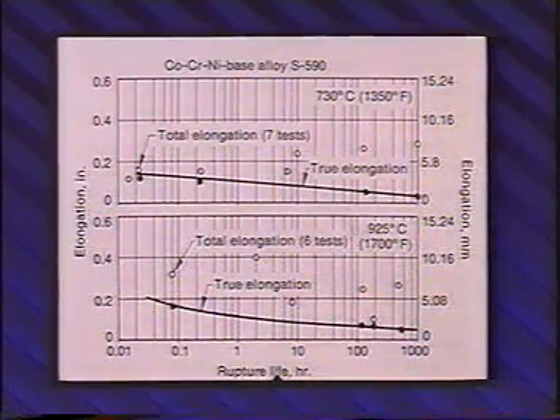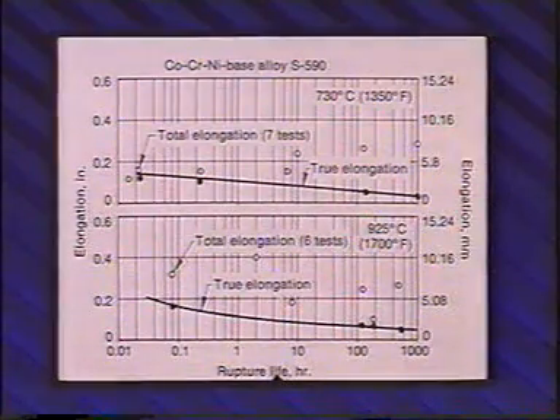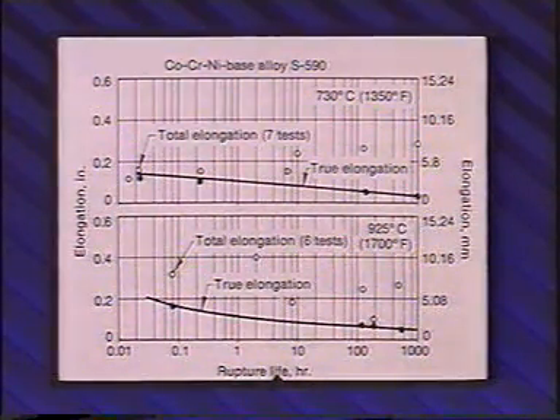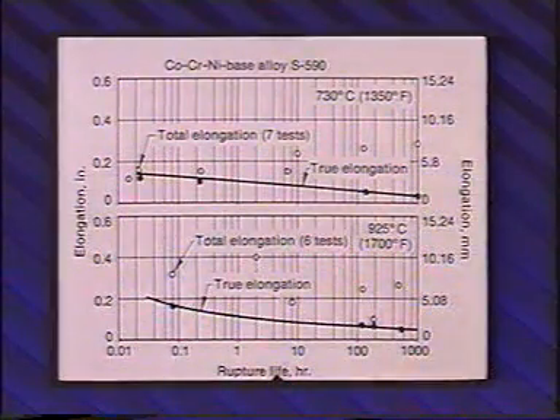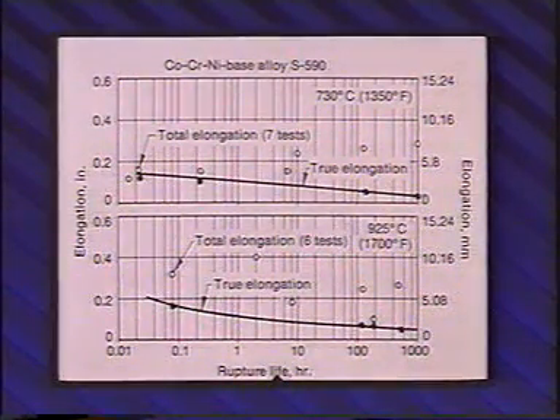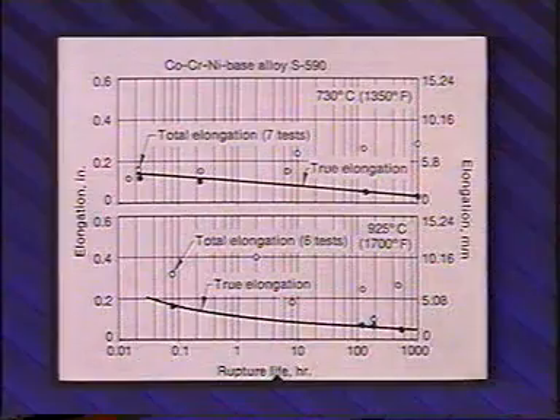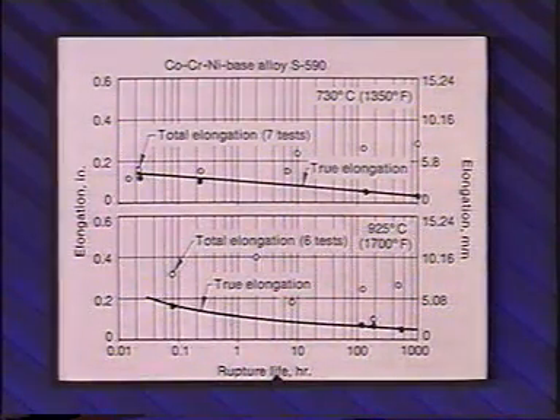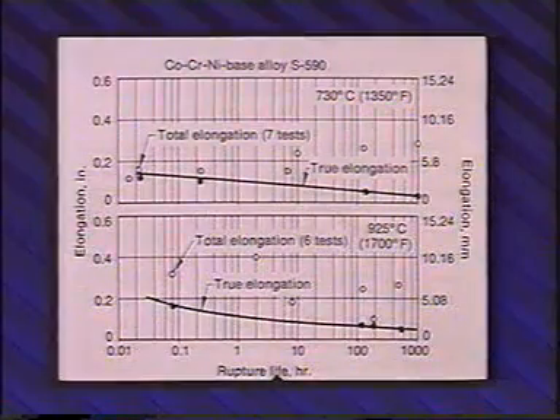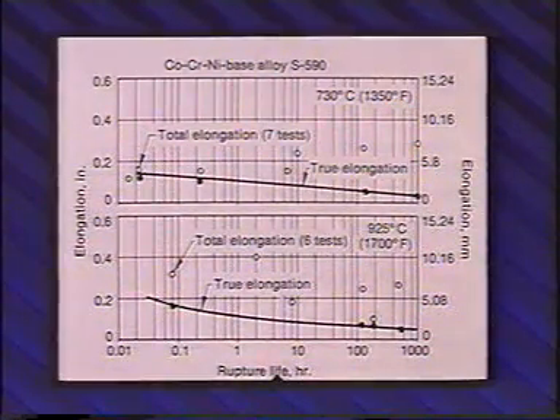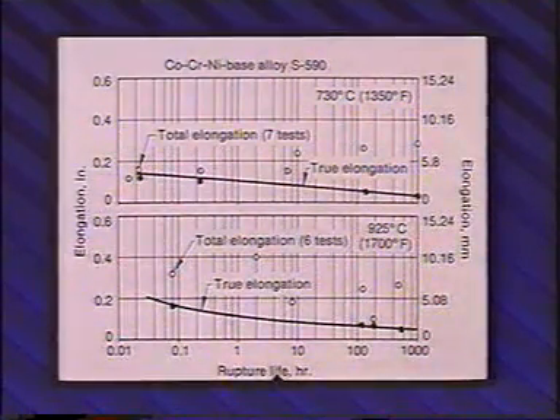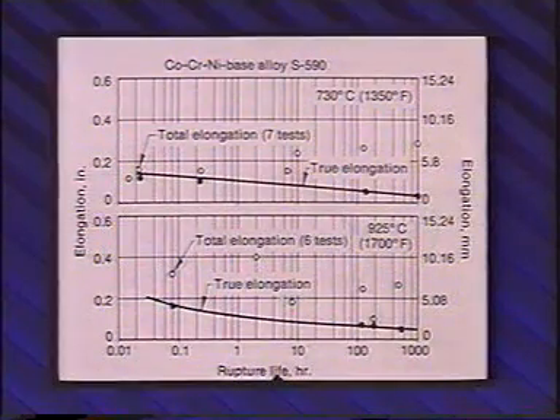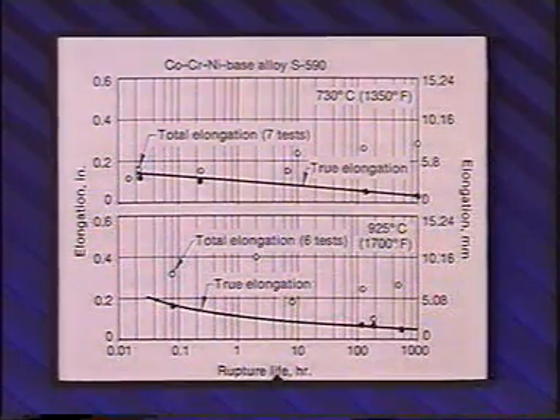For the nickel-base alloy S590 at a testing temperature of 1350 degrees Fahrenheit, the true elongation to the end of stage 2 shows a fairly straight line. Total elongation is indicated by an appreciable scatter of data points. At 1700 degrees, total elongation shows a similar scattering of data points. Therefore, true elongation generally provides the more accurate representation of ductility in metals at elevated temperatures.